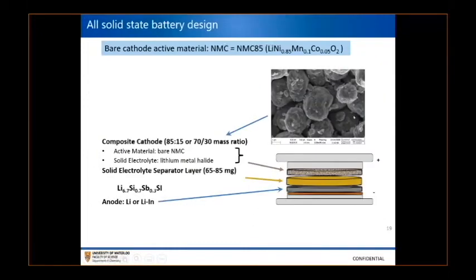I showed you actually a picture of what they look like here. So these are the cathode active materials, and these little lumpy parts are the electrolyte, which is literally coated and packed onto the cathode active material. So we assemble cells in our lab on a routine basis where we have our cathode composite, which is the electrolyte and the cathode. We have our separator, which is the material I just told you about. We marry this with a negative electrode, either lithium or lithium-indium.